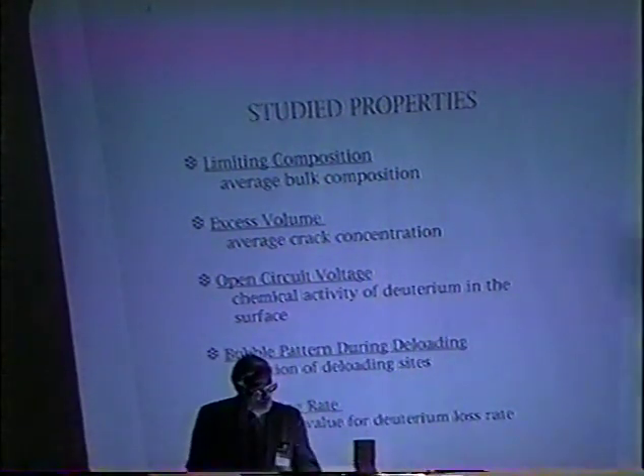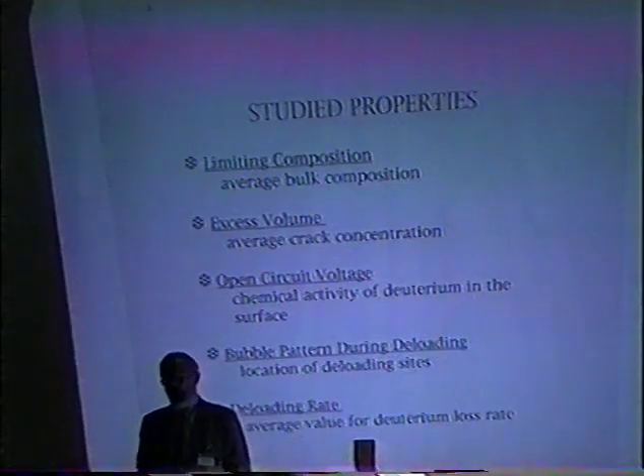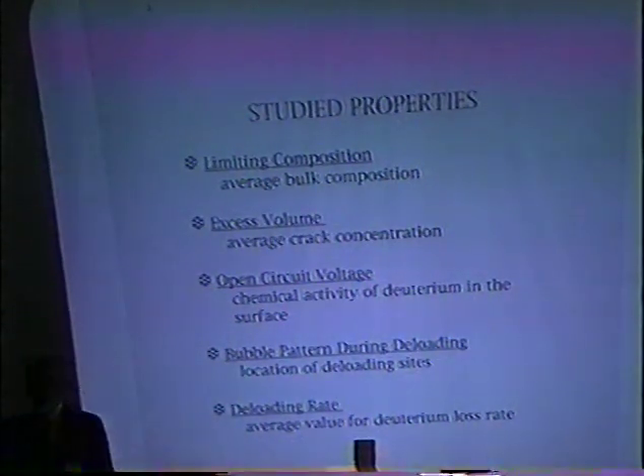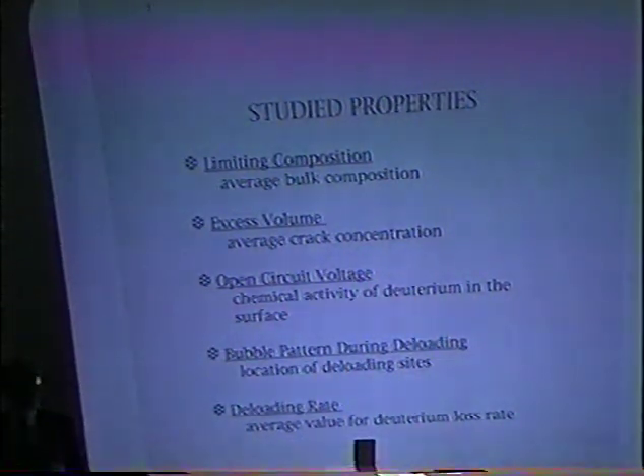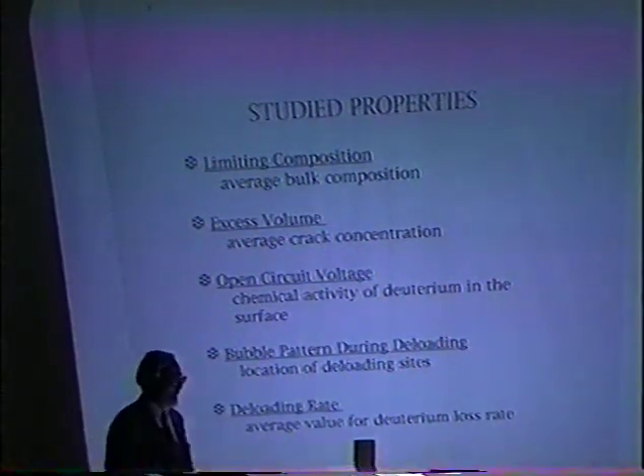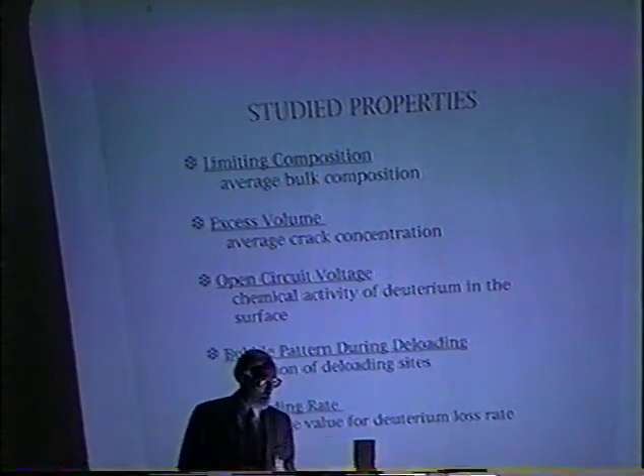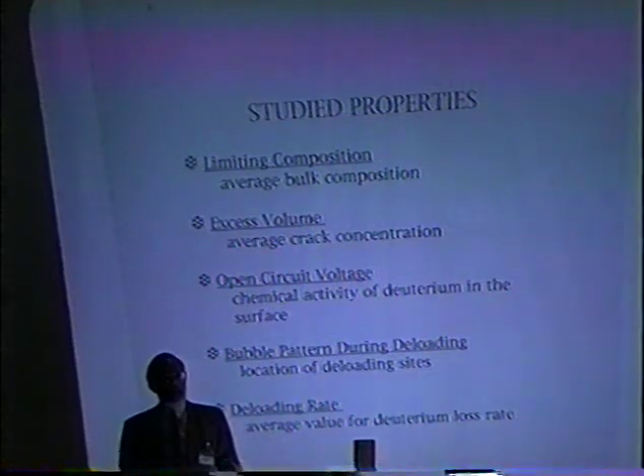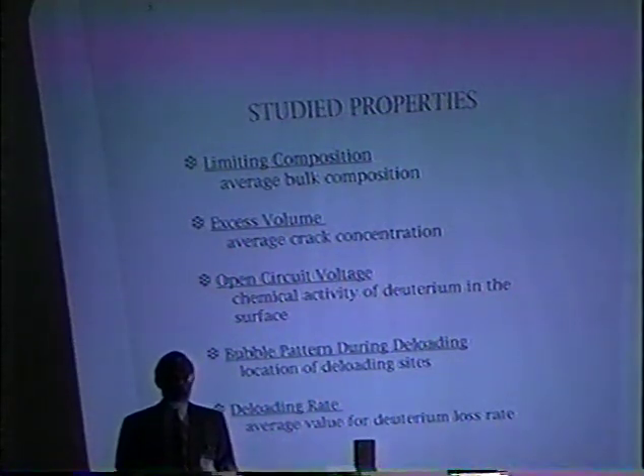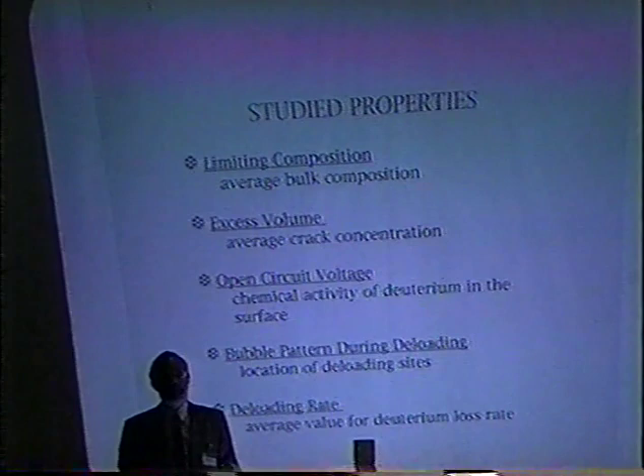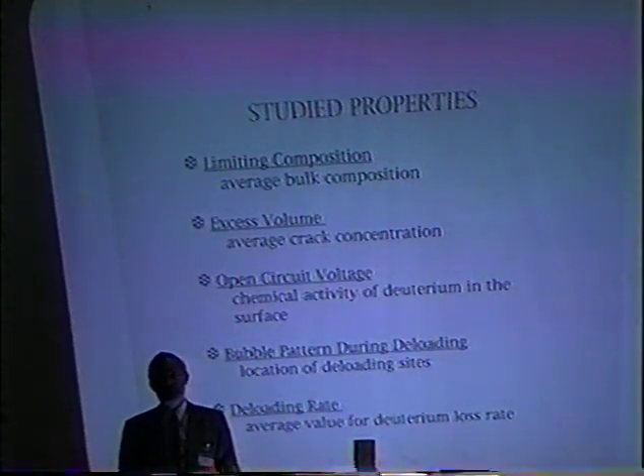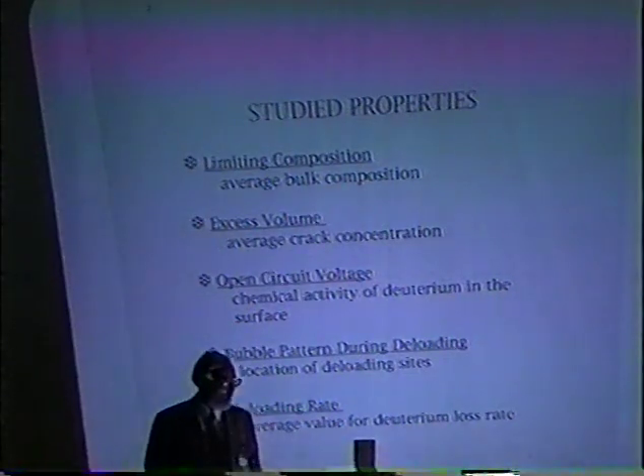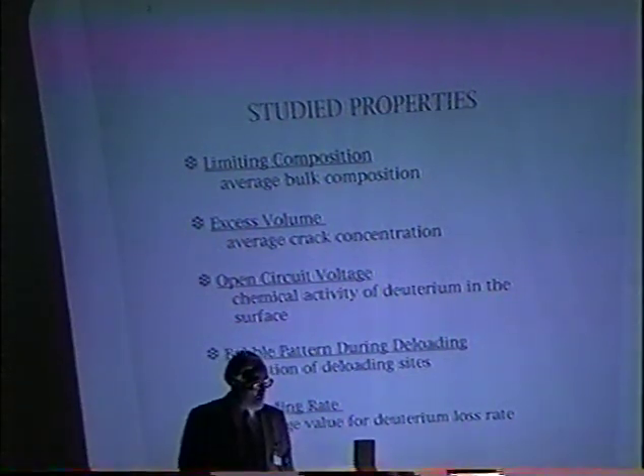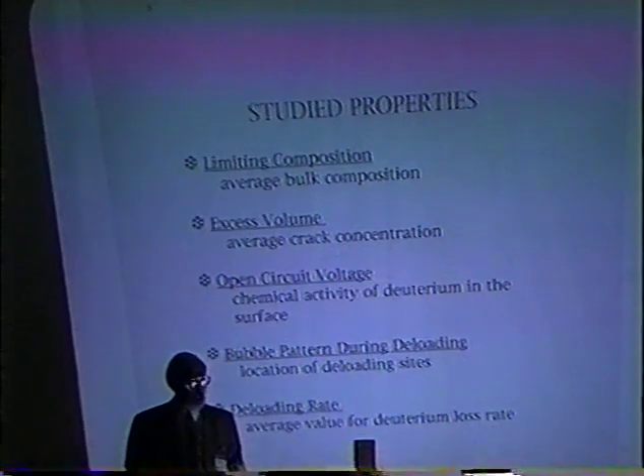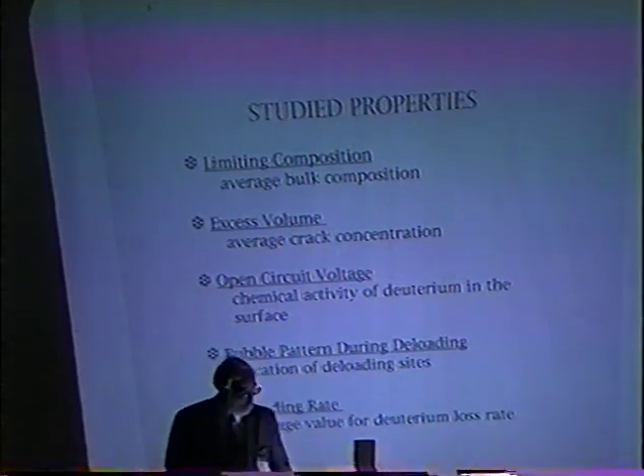The open circuit voltage is a way of measuring the chemical activity of hydrogen in the surface. And if I have time, I'll show you evidence that indicates that the production of excess energy is preceded by the formation of a phase on the surface, which is quite different than normal palladium deuteride. And the excess energy forms only if that phase forms.